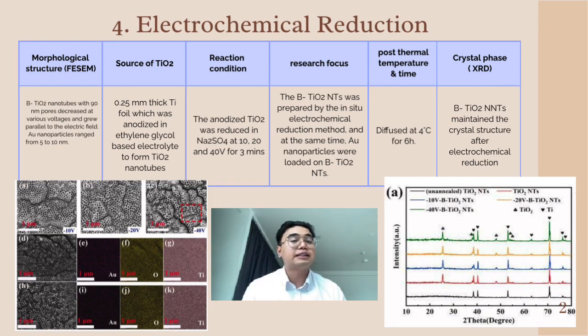The fourth synthesis method is electrochemical reduction. The morphological structure in the photos illustrates the prepared sample's integrity and nanotube morphology. In figures A to C, the black TiO2 nanotubes reduced at various voltages were well arranged with approximately 90 nanometer pore size and grew parallel to the electric field.